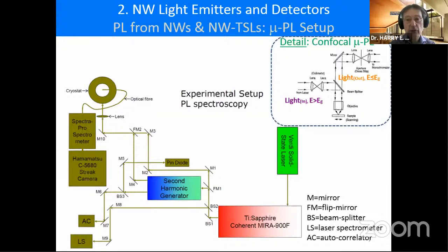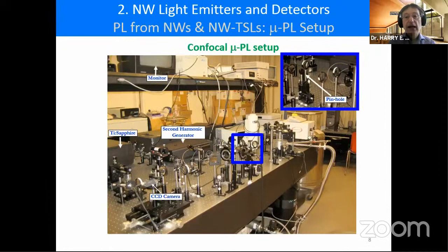We can do time-resolved studies with the streak camera, and we can do these measurements at very low temperatures. And lastly, with the confocal setup, we can look at individual nanowires and study along their length and so forth. The confocal setup is shown on the bench here, and one of the key things is the pinhole, which enables us to scan and look for individual features and parts of wires. In fact, we reported some work where we put wires on TEM grids, and we looked at heterostructured wires, and we could actually get luminescence from different parts of the wire and correlate that with the TEM. I won't be talking about that today, but that's the kind of capability of a system like this.